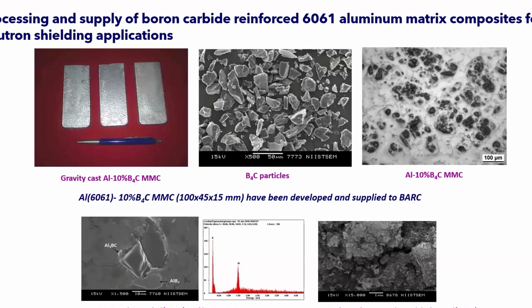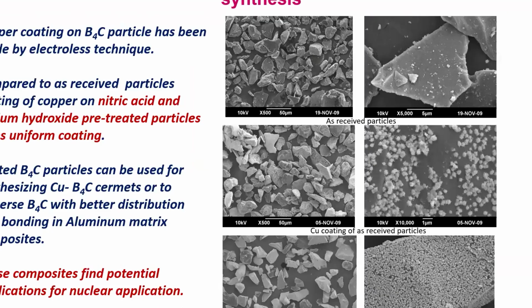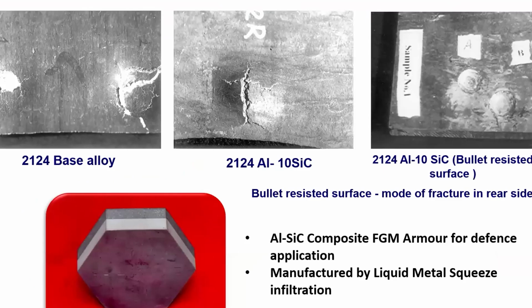So similarly, to improve the wettability, we can go for some coating, especially copper coating over the boron carbide particles. And these aluminum alloys are also used in lightweight armors, especially with SiC particles embedded into the armors, because it absorbs energy when a bullet hits. So they incorporate these ceramic particles, and we can even make a functionally graded armor like this.